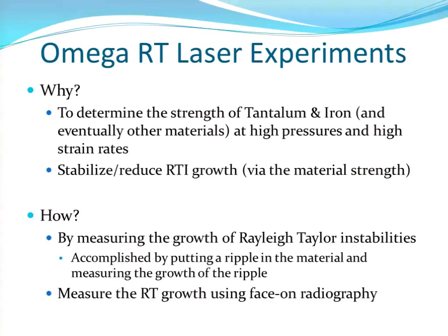So why are we doing this? It's to determine the strength of these materials at really high pressures, which you can't do very easily — that's why we need these laser facilities. We study RTI growth via the material strength, which has that application to fusion energy. We put a ripple on our sample, impact it, and watch the growth of this ripple. Comparing that to models, we can get a measurement of strength.